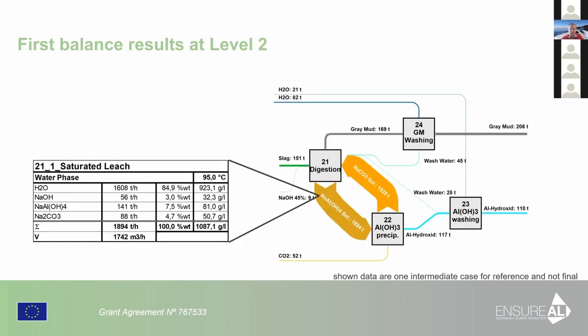So going from the first level to the second level, here you see that the core, or the biggest mass and material stream, is between digestion and precipitation, where we are circulating bigger amounts of solution to keep the process running, and the slag and the outflows are smaller. And so the important knowledge of that is that this core circle within the process defines at the end of the day the size of the plant, the costs of the equipment, and so on.